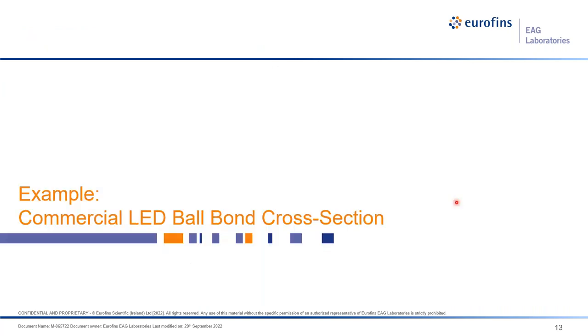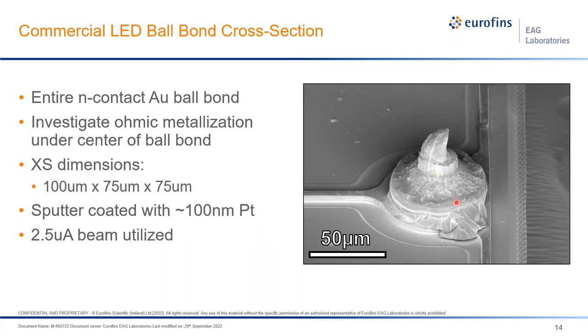So let's first look at a couple examples of where we can utilize the P-FIB for medium to large size cross sections, the first being sectioning of an entire ball bond. In this case, we're gonna look at a commercial LED ball bond structure, and we're gonna cross section the entire n-contact. You might wanna do something like this if you're interested in investigating the ohmic metallization underneath the ball bond. Maybe there's an issue with a connection between the outside world and your device here.